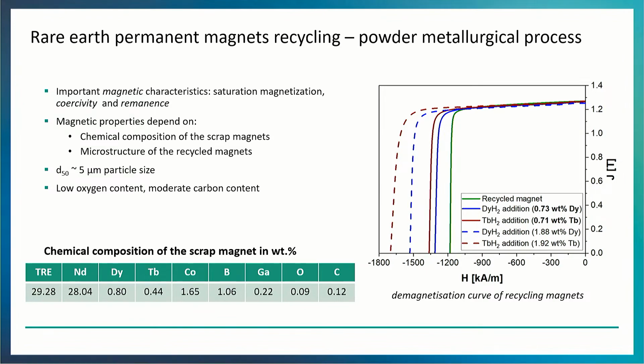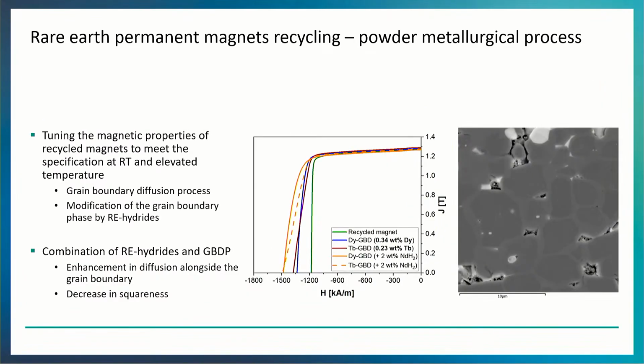These magnetic properties, as I said, depend not only on the chemical composition of the scrap magnets, but also on the microstructure of the recycled magnets. And you also have a certain particle size, and there's a whole to-do list which you have to know when you're producing new magnets. Also, the oxygen content should be there, but not too high, and the carbon content should be moderate. So it is a very complex composition and a complex procedure to produce them.